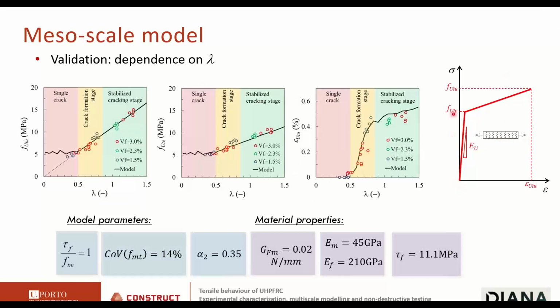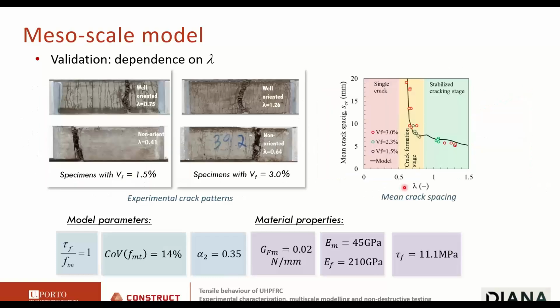And if you remember, where did we come from? So we wanted a simple model to put in our finite element models that is bilinear, that is described by the conventional limit of elasticity, tensile strength, described by the strain at the onset of localization. And you see these three parameters here in these three plots as a function of the fiber structure parameter, that parameter that lumps all the effects of the fibers. And we see that the model describes this very well throughout a wide range of values of the fiber structure parameter, and even the mean crack spacing.